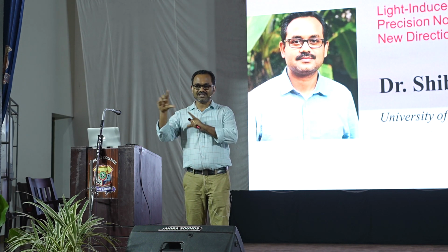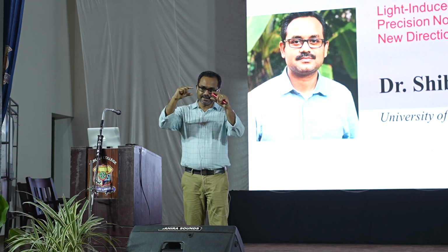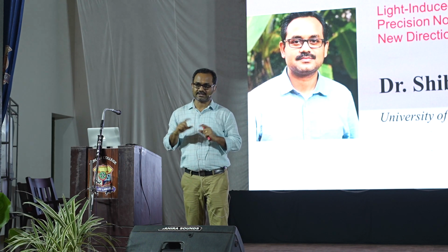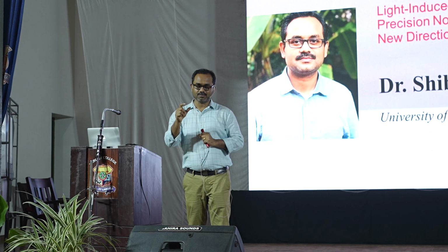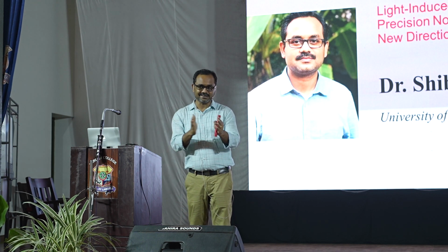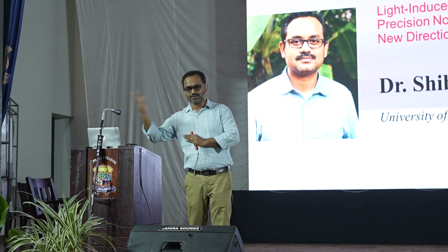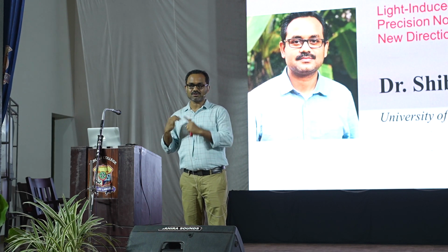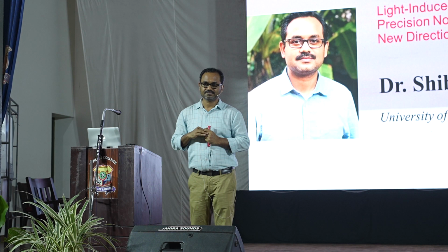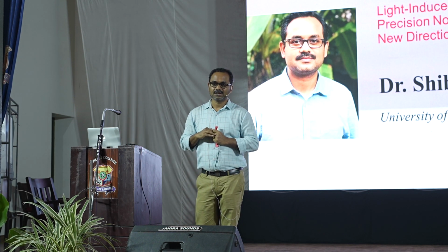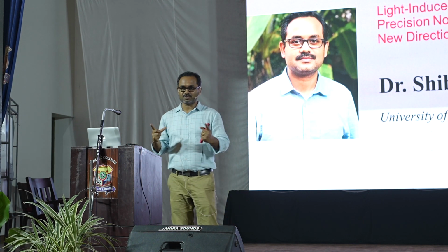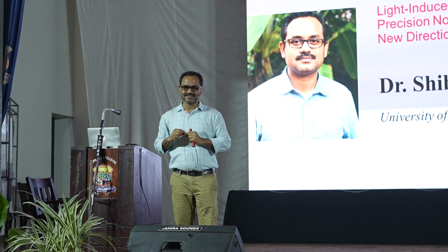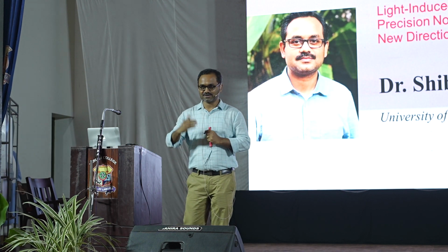That is where we have a little limitation. Making the core as Au25 itself is very fast work for us, and based on the Au25 polarity, it works in DCM only. If you try to change the polarity of the solvents, either the cluster will decompose or it may not be stable, and it can decompose and give different structures. Yeah, that is also possible. But as I told, we have only limited resources, limited students. Yeah, I understand. That is also a possibility.